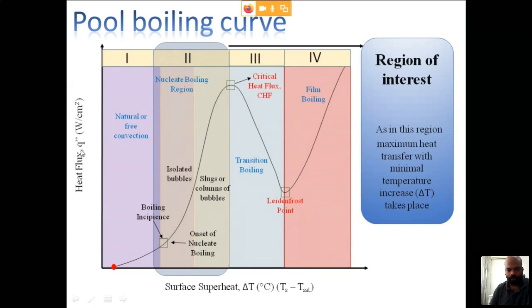Now Q, this heat flux divided by surface superheat, will give the heat transfer coefficient. That is nothing but the slope of this curve. So the slope of this curve is very important, and this point is called critical heat flux. As you can see, the onset of nucleate boiling and heat transfer are the performance parameters. These two parameters will give you a measure of the performance of the system, but this critical heat flux is not a performance parameter, it's the safety parameter.